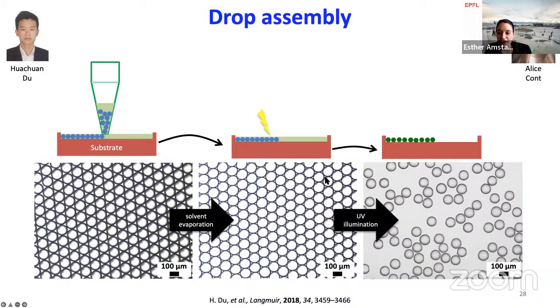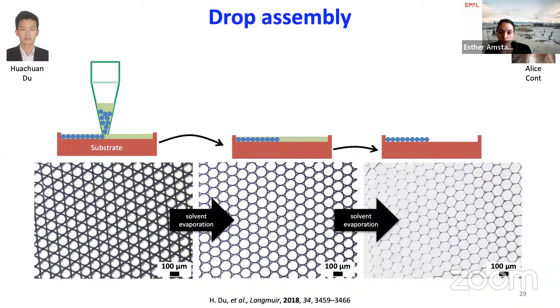We did something very similar with an important difference, though. We produced the drops in exactly the same way. We deposited them on a substrate, but then we let the surrounding oil evaporate before we initiate the polymerization reaction. As the oil evaporates, the drops deform because they want to minimize the interfacial area between the drops and the air. So they become hexagonal prismatic particles.